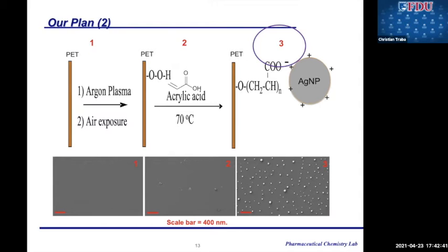The immobilization of silver nanoparticles occurred naturally and through electrostatic interactions. This is because of the negative charge on the grafted surfaces from the deprotonation of carboxylic acid groups in solutions with pHs of higher than 4.5, and the positive charge on silver nanoparticles.